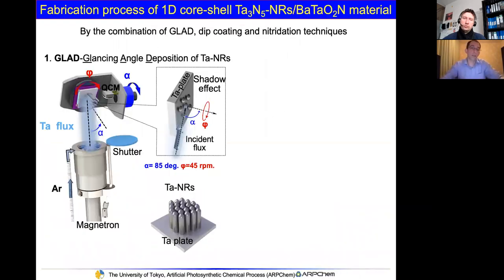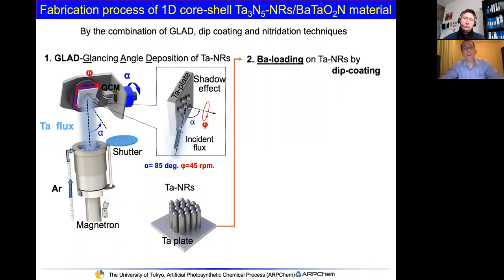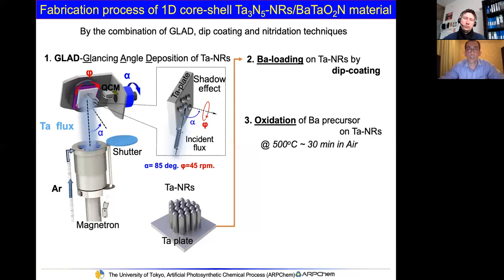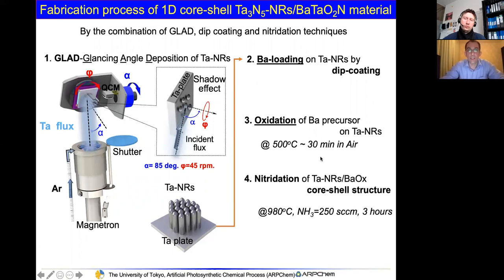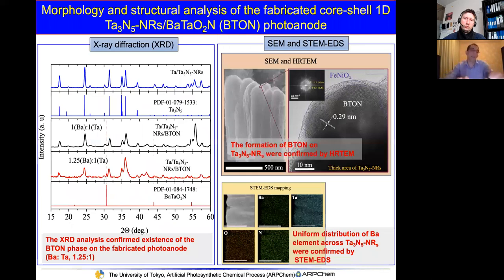So then again, we started the deposition of the tantalum nanorods, this time just metal. I will explain why. Then we load the barium-rich precursor on the tantalum nanorod by using the dip coating technique. Then follows the oxidization of the barium precursor in order to take off the organics from the barium-rich precursor. And then the final stage is the nitridization to make the core shell nanostructure. Okay, and now